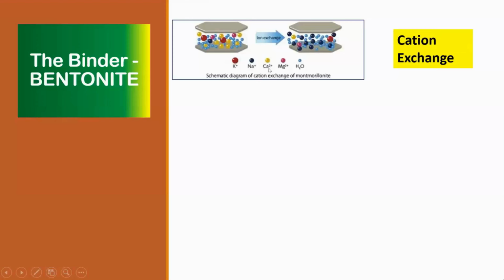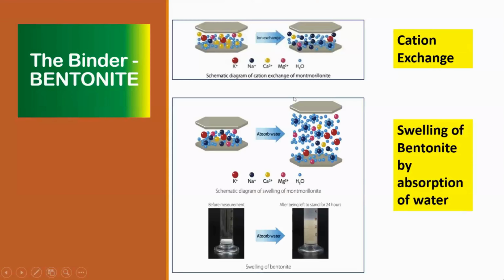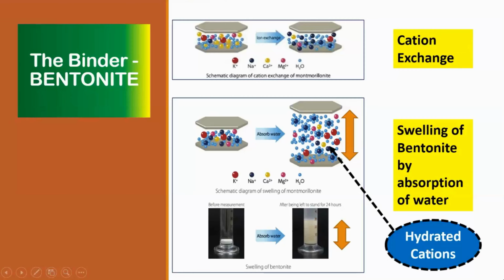So if you want to convert a calcium bentonite into a sodium bentonite, you use soda ash and then water. So there will be an exchange of sodium into the calcium space. Now this water also is going to increase the distance between the two crystals. This is called swelling. When the absorption of water takes place, H2O molecules occupy some space and then increase the distance between the two crystals. And then you see that this is the expansion that is taking place, swelling, due to the hydrated cations.